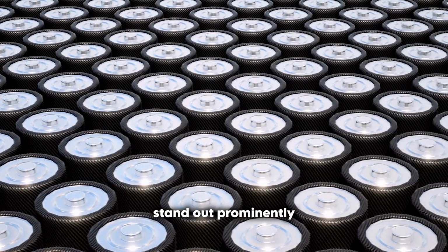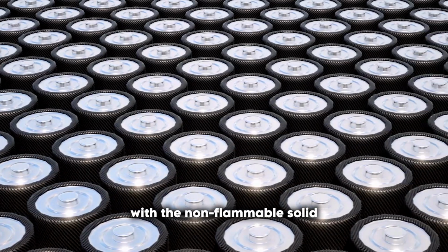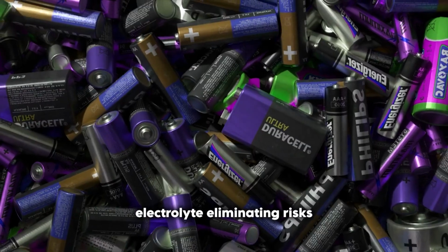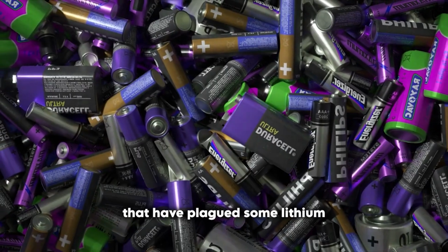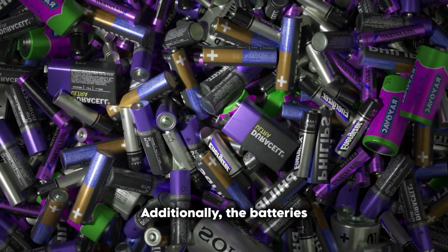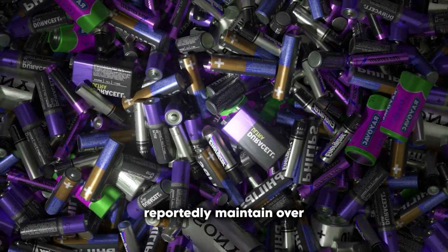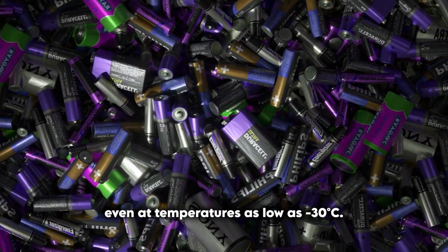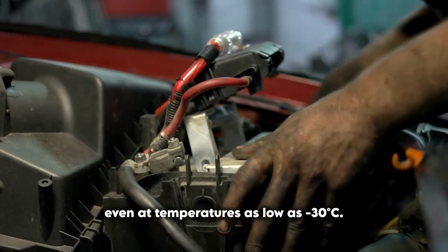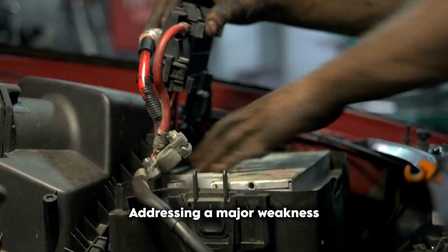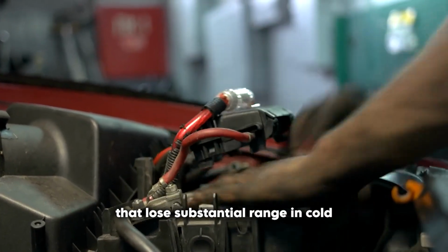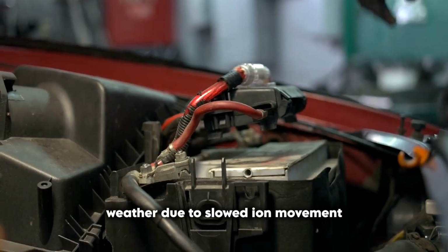Safety features stand out prominently in the company's messaging, with the non-flammable solid electrolyte eliminating risks associated with thermal runaway that have plagued some lithium-ion incidents. Additionally, the batteries reportedly maintain over 99% of their capacity even at temperatures as low as -30 degrees Celsius, addressing a major weakness in current electric vehicles that lose substantial range in cold weather due to slowed ion movement in liquid electrolytes.